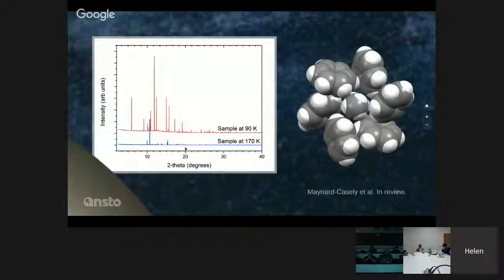So exactly these two pictures are those two photographs, but through the eyes of diffraction. This is your benzene. So here's your couple of benzene peaks here. So it's a nice, simple crystal structure. And when you introduce the ethane, and in fact, we cooled down to 90 Kelvin because that's the surface temperature, so that's the -180°C at the surface of Titan, we get a brand new crystal structure. And in fact, you can see it's very different from this pattern. Hopefully that's not too hard to see.